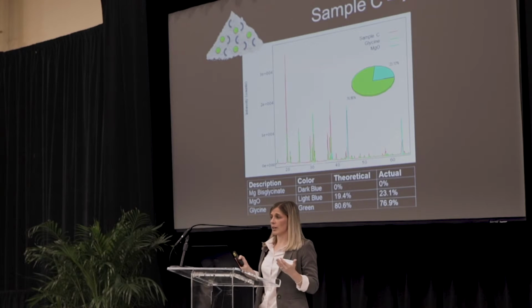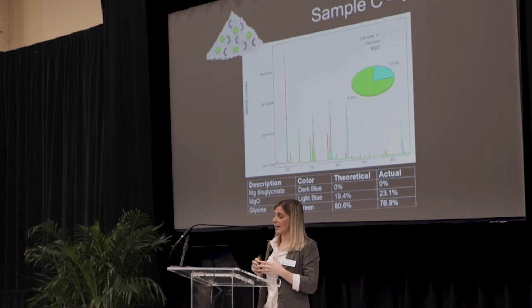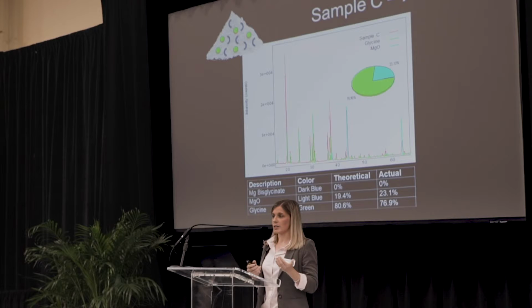So then finally, if we look at sample C, we can see that it's just made up of magnesium oxide and glycine, and we can tell that from comparing the fingerprint of sample C, the red data, to the fingerprint of glycine and magnesium oxide. And again, they completely overlap, letting us know that we've identified all phases present in this compound. And you can see again that the theoretical numbers and the actual numbers that we determine from the analysis are very close.